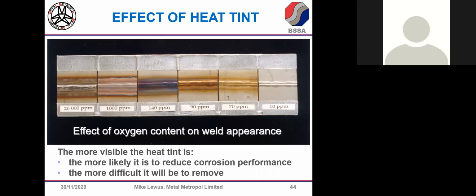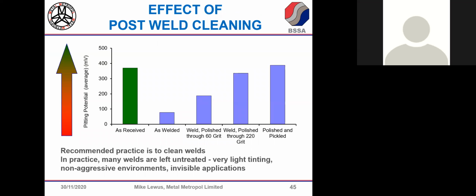A quick point about heat tint. If you've got any sort of discoloration at a weld seam, what you know you've got is a thick chromium oxide layer beneath which you've got parent metal that's depleted in chromium. So you know that if that material was subsequently exposed in an aggressive environment like a marine environment, chloride is going to get to that depleted parent surface, the parent surface depleted of chromium. So it'll perform much worse than it otherwise would. I'm going to jump through there.